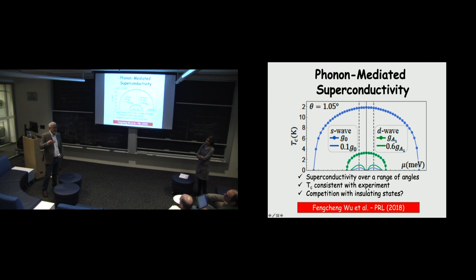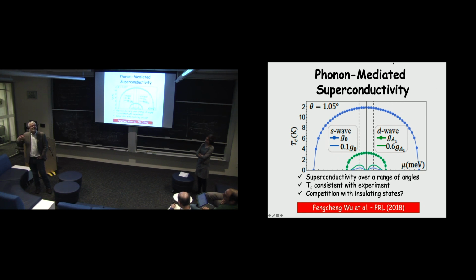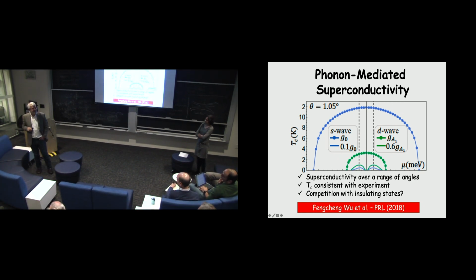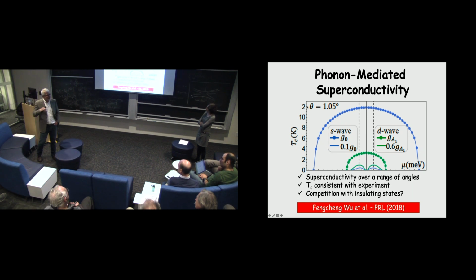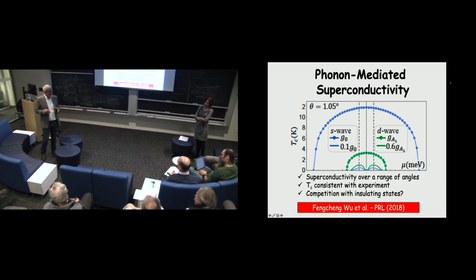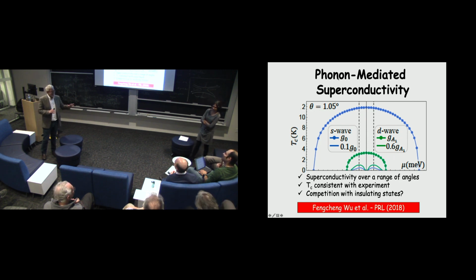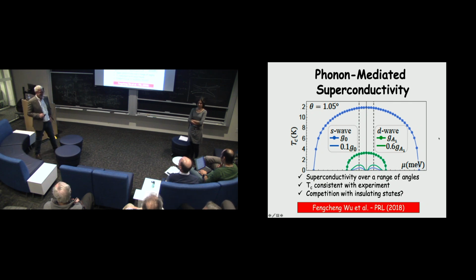And as many of you know, it's the retarded nature of phonon-mediated interactions that makes superconductivity work in many metals, and that's not here. So certainly Coulomb effects and lattice-mediated effects, which are always both present, will compete in a different way here. So I'm optimistic that we're going to be able to understand, maybe just by continual improvement, we're going to come to a consensus, at least, about what's responsible for superconductivity in this system, but we're certainly not there yet. Yeah. Thank you.